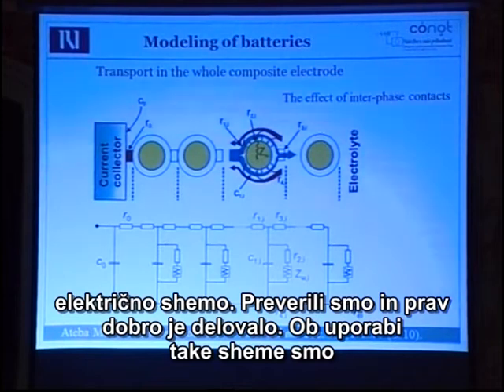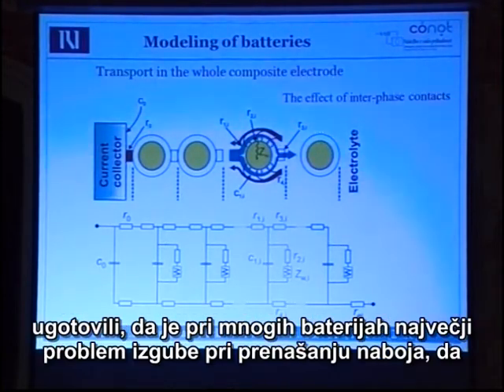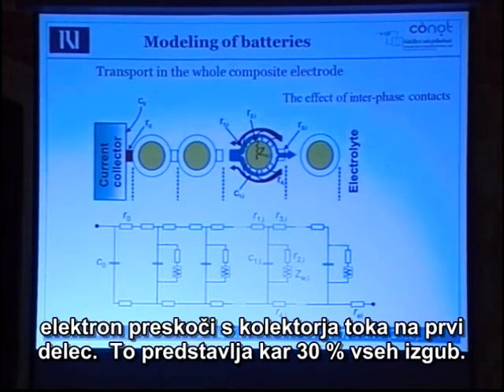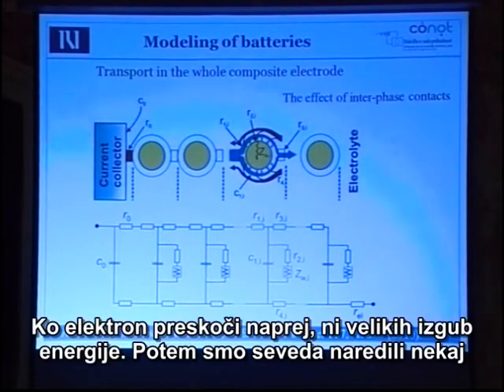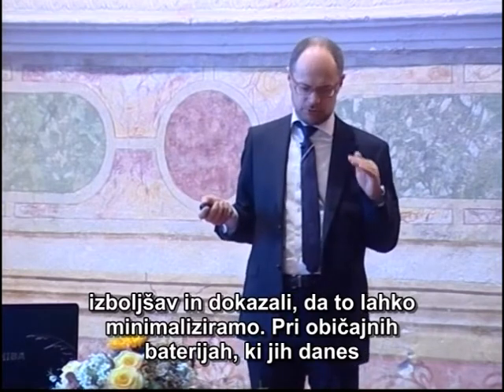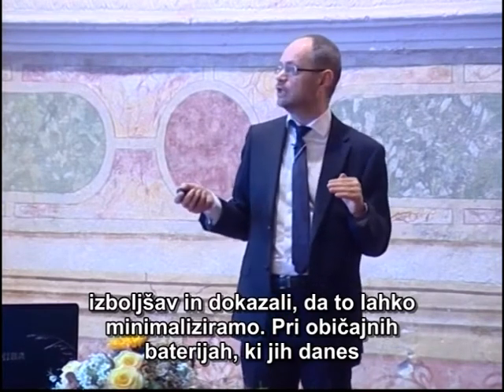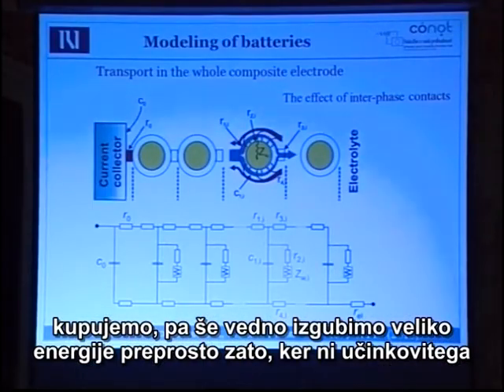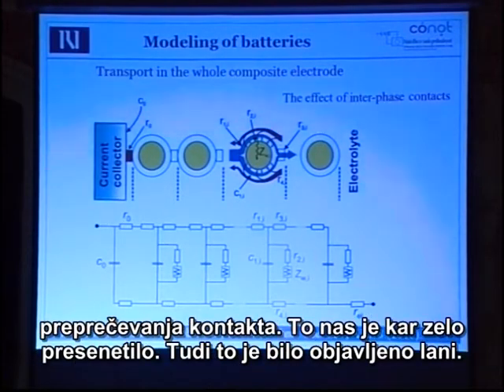For example, using such a scheme, we found that in many batteries, one of the bigger problems of charge transport is that 30% of energy you lose when the electron jumps from the current collector to your first particle. There is not a lot of loss of energy when the electron jumps further from one particle to another. But the most energy is lost at the jump from the current collector to the first particle. Then, of course, we used some improvements, and we showed that this can be minimized. But in normal batteries, the batteries that you buy today, you will lose about 30% of your energy simply by not having this contact optimal. This was quite a big surprise, I would say. This was published also last year.